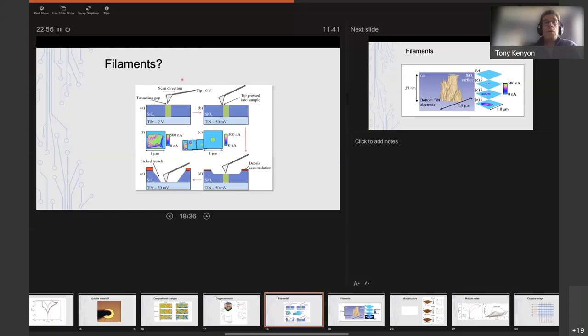The other thing we can do is we can apply an electrical bias between the tip, if the tip is conductive, and in this case, bottom electrode that this oxide is deposited on, and we can map out regions where we have high or low conductivity. And if we do that on one of our samples here, we can see that at the top here, we see a region that has much higher conductivity than the surrounding region. Okay, so we're measuring a current here about 500 nanoamps and essentially zero all around it.